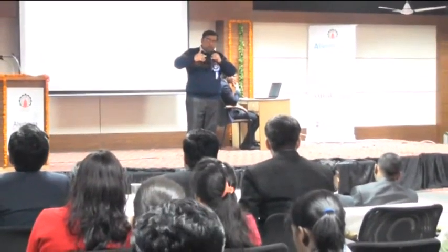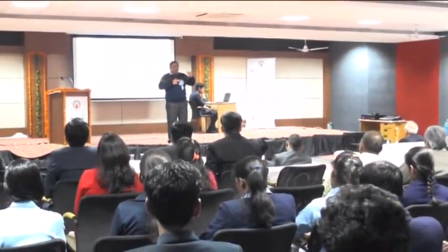So in that case, if I am able to demarcate the volatility of the PPG as opposed to the PMSSQ, what will happen is that at a lower temperature, the PPG will evaporate altogether, and wherever the PPG was there will be creating hollows because the PPG has evaporated. So in this case, what we are doing is the following. Can you go to the next slide?